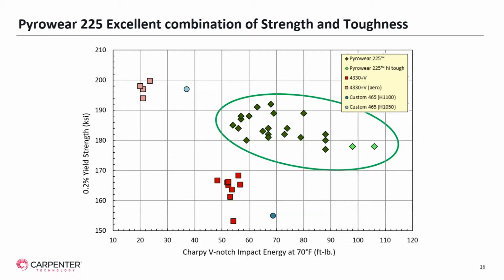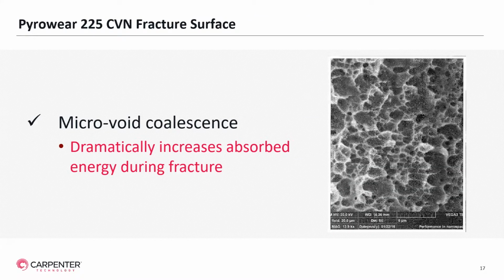in this grade. If we heat treat it a certain way, the light green diamonds are indicated as Pyrowear 225 high tough, where we're able to reach 106 foot-pounds of impact energy and a yield strength of about 178 KSI. We think that the reason for the dramatically increased impact energy is due to microvoid coalescence, which we see quite often on the fracture surfaces of the failed Charpy V-notch samples.